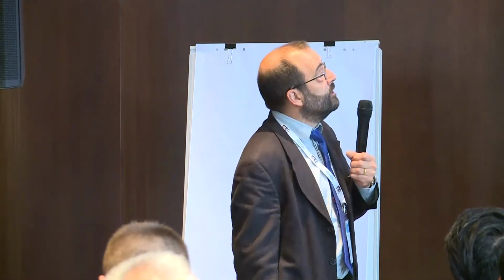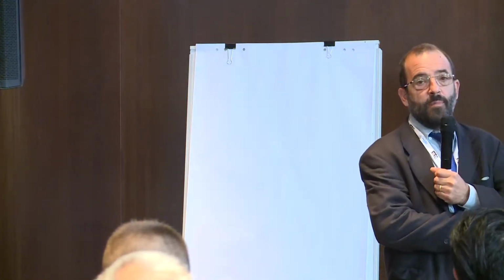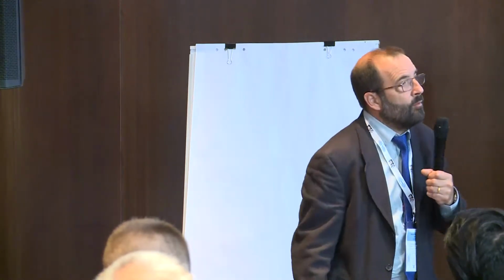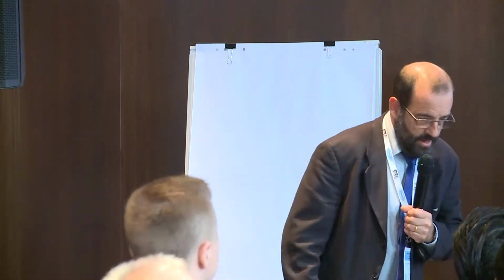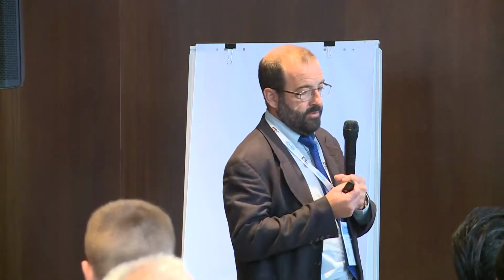The testing machine is relatively small and compact. The weight is 1,200 kilograms. It has a capacity of 50 kilonewton statically and dynamically. So any load range can be tested. The loading frequency depends on the specimen stiffness, since the machine runs exactly in the resonance frequency. So depending on the specimen, the frequency is between about 980 and 1040 hertz. So we also have the advantage that if there's any change in the specimen, we see that in a drop of the testing frequency.